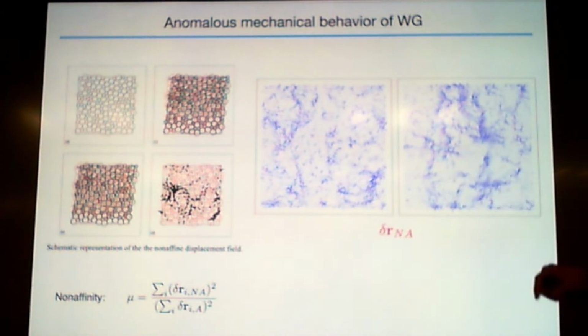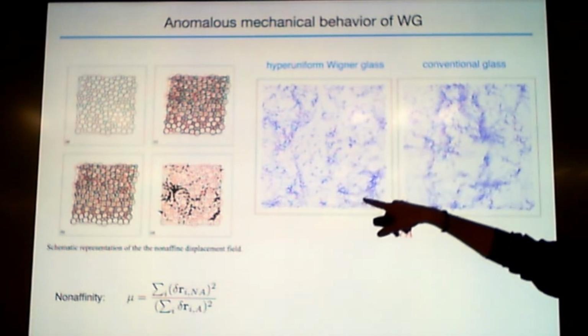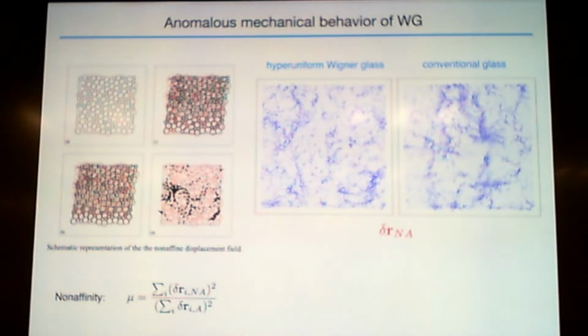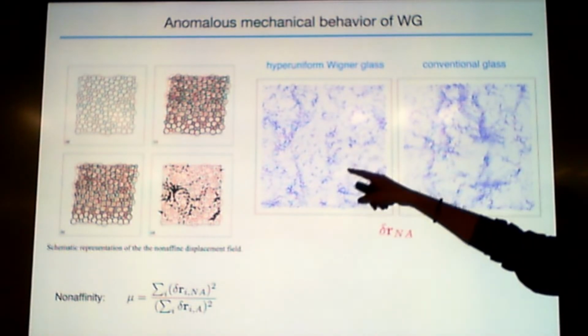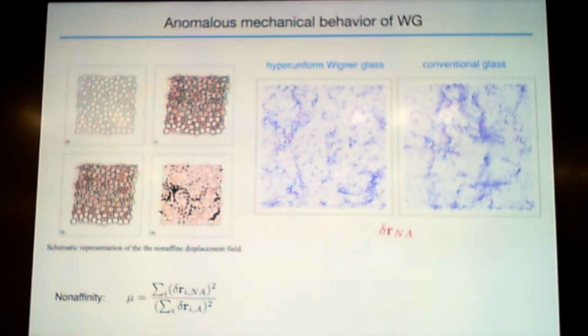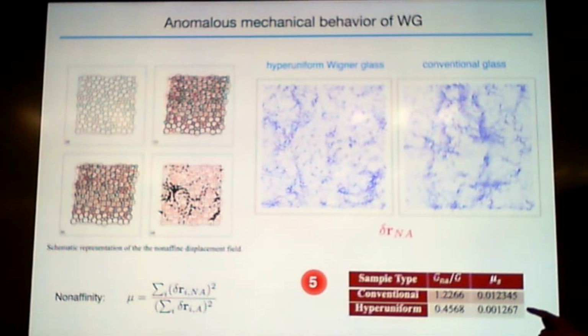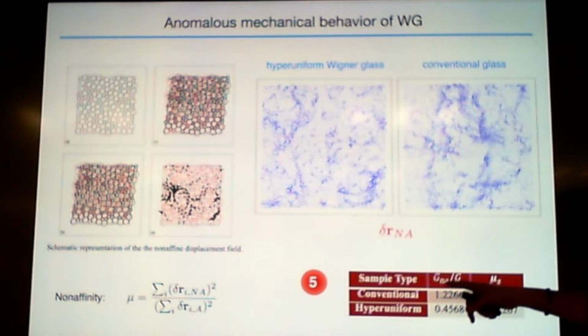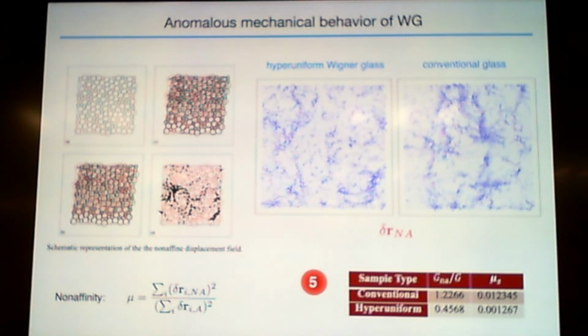So this is the displacement field. Usually I ask which one is which, but let's skip that. The hyperuniform glass is less coherent than conventional glass. If you excite the conventional glass, if you shear it or whatever, the particles will displace along these arrows more coherently. Whereas in hyperuniform glasses, it looks more brittle. That's what I was mentioning: the non-affinity in hyperuniform glasses is an order of magnitude smaller. They are more affine. It's almost like a crystal. Well, in a crystal it's 0, but we are getting there. And this is the shear modulus, the non-affine part of it. It's also smaller. It's a novel type of glass, if you want.